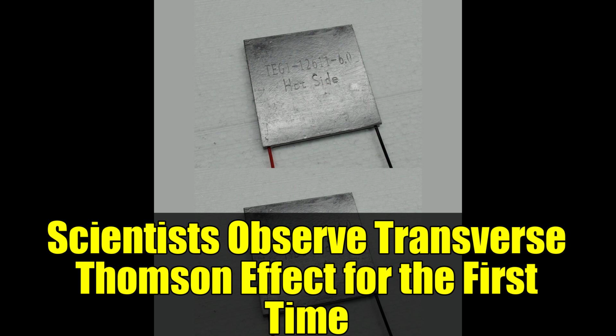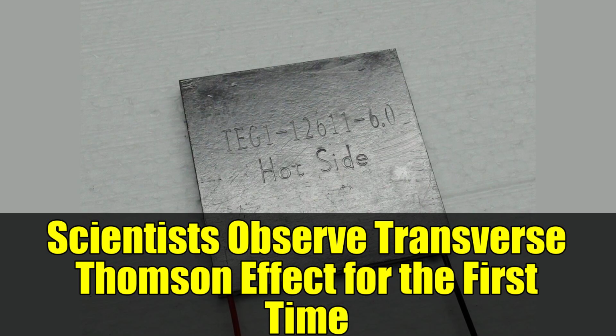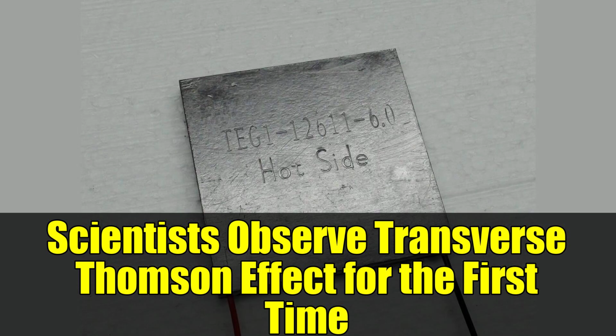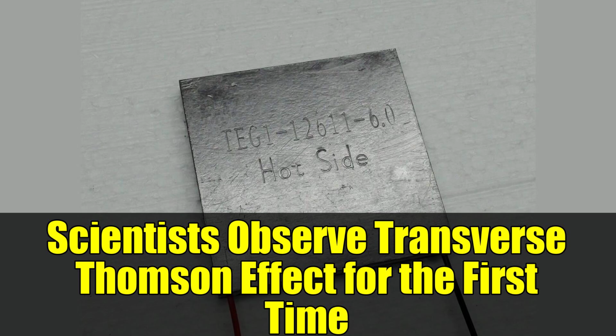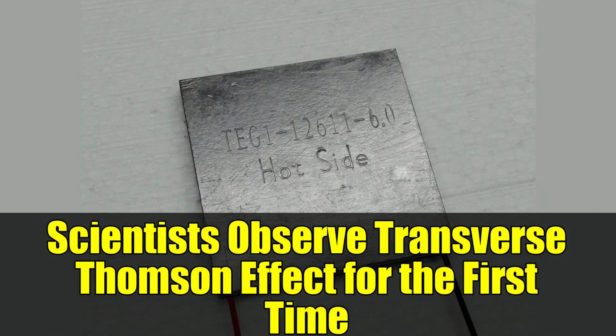The challenge of isolating the Transverse Thomson effect was monumental. To overcome this, the research team employed advanced thermoelectric imaging techniques, specifically lock-in thermography. In our experiment, we used an infrared camera to observe the thermal response of the sample when a periodic electric current was applied, Uchida explained. By extracting the temperature modulation component that oscillated at the same frequency as the applied current, they were able to isolate the thermoelectric signals from the Joule heating.